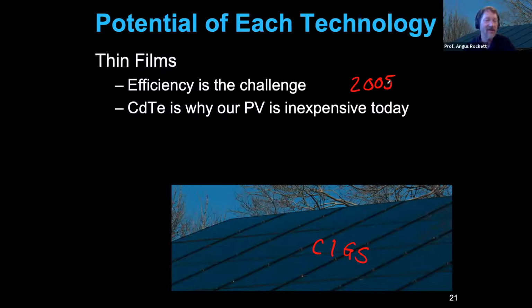And so it has gone to the point where we've gotten down to about 40 cents a watt. First Solar is still making money at 40 cents per watt. The silicon community struggles because that's right on the edge of what they can manage. And it's very difficult for First Solar as well. But 40 cents per watt is the current sort of wholesale rate. So cadmium telluride has been responsible for a lot of the price drop and a lot of the increase in the market worldwide. For copper indium diselenide, I think there's still hope, and we've had some exciting results lately that I'll talk about in regard to that.